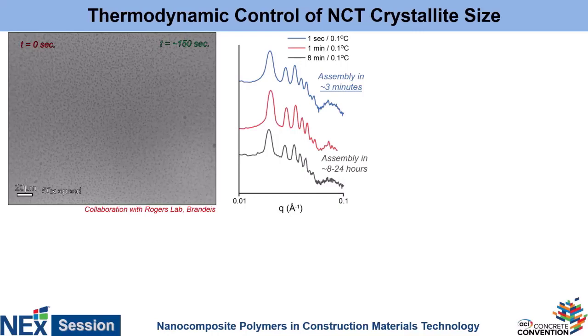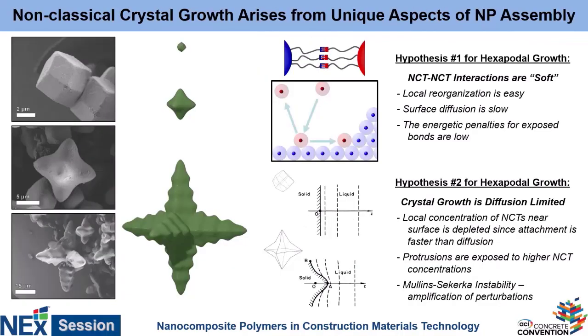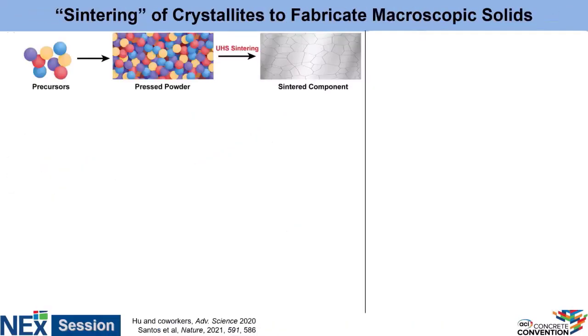The reason this is important is twofold. First, it allows us to study these things in a manner much more amenable to scale-up. Second, it allows us to tune the overall size of those crystallites — we can make those rhombic dodecahedra very small or very large and everything in between. But these structures at their largest were about 100 microns. That's really interesting for fundamental studies of crystallization and assembly, but not so great for actually making a macroscopic material. A student said — how about instead of a single crystal the size of your head, we make a polycrystalline material? We know from basic metals and ceramics that if you have a nanopowder and you heat and squeeze it, you can turn that nanopowder into a sintered bulk material. Our particles are held together by just hydrogen bonds, so if we take those single crystal structures and centrifuge them at about 20,000 RCF for about 10 minutes at more or less room temperature, they do indeed densify.